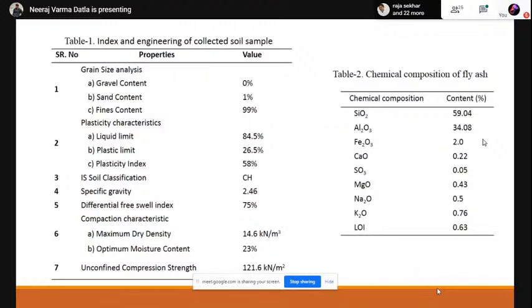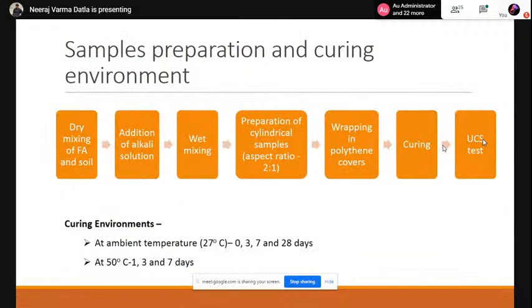And these are the index and engineering properties of the collected soil. It contains more fines, up to 99%. The liquid limit is also very high, and as per the IS soil classification system, it is classified as clay with high plasticity. And this is the chemical composition of fly ash. It has high silica and alumina content, so it is suitable for geopolymerization synthesis. And its calcium content is very low, hence it is classified as class F fly ash as per the ASTM classification system.